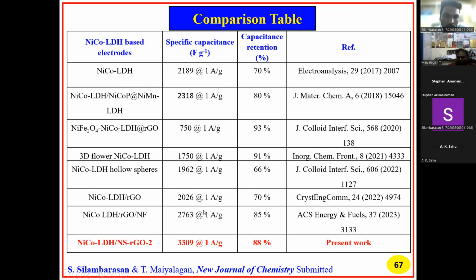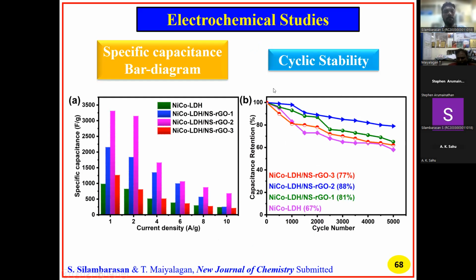Next, we compared with previous literature our nickel cobalt LDH with NSRGO composite, 3,309 at 1 ampere per gram, with 88% retention. Next, the bar diagram of specific capacitance, current density versus specific capacitance, is shown here. The cyclic stability for 5,000 cycles we measured. So the retention percentage overall for sample 2 is 88%.